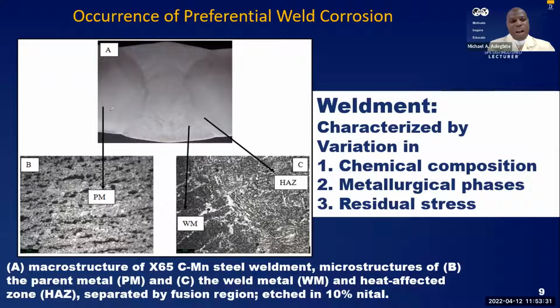So in essence, the weldment is the entire region around the weld. The weldment is characterized by variation in chemical composition, that's the weld metal. The weld metal composition is different. Then the metallurgical phases being present are associated not only with the weld metal, but also, and much more, the heat affected zone. And of course, the residual stresses associated with non-uniform cooling.